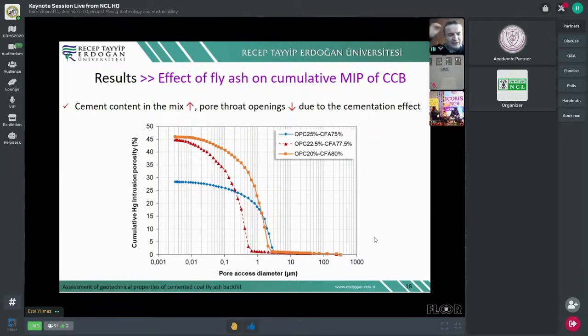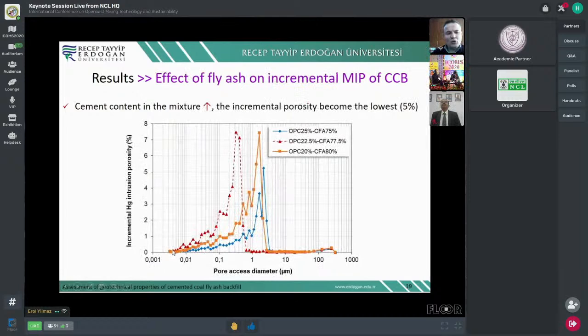And I'm coming to the end of my presentation. Last 3 to 4 slides remain. And here also the Mercury intrusion porosimeter results. Here the cumulative MIP results. You can see that with the increase of the cement in the backfill, pore throat openings decrease due to the cementation effects. Blue line, you will see the porosity is getting down, and also the pore diameter shifts to the finer zone, approaching the origin. Also here the incremental